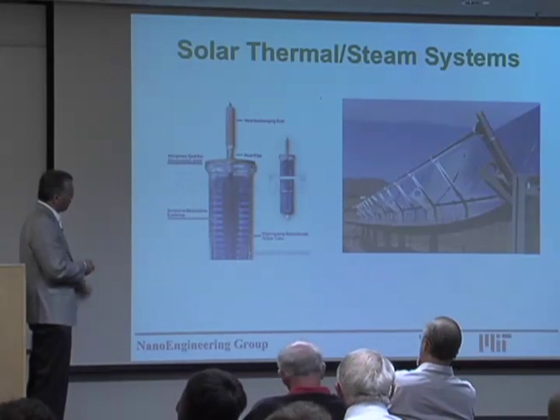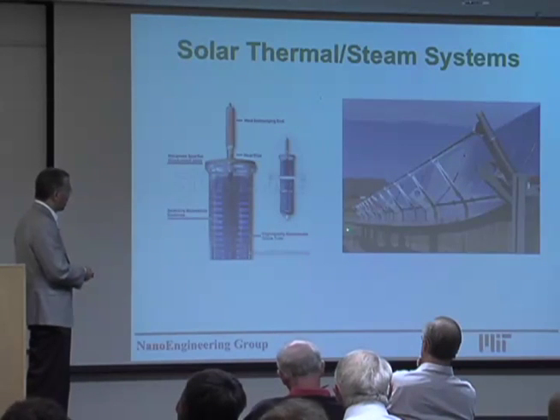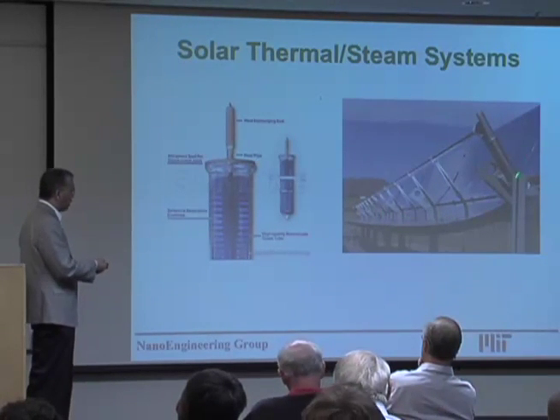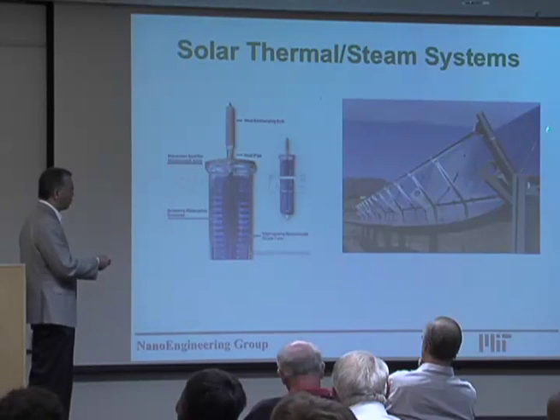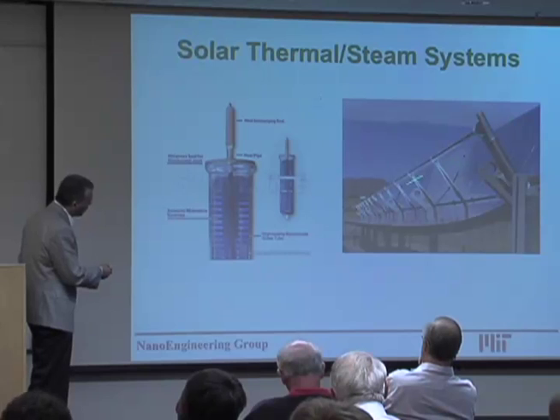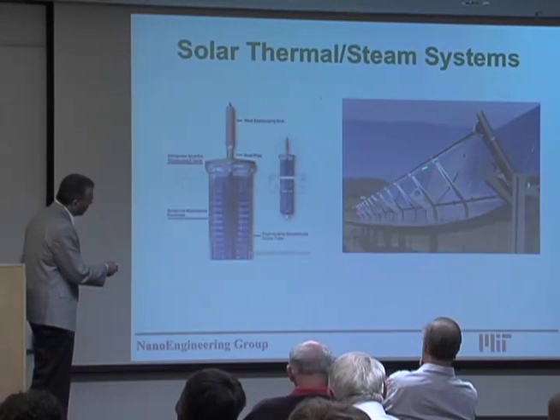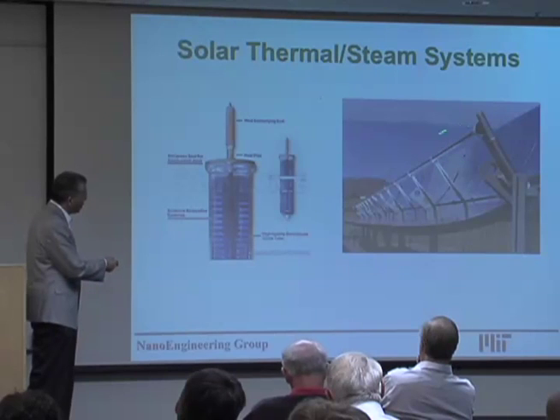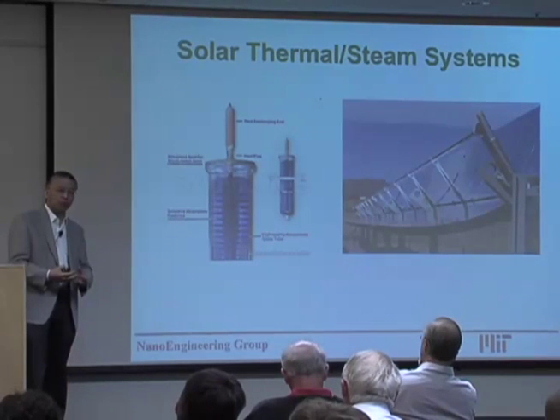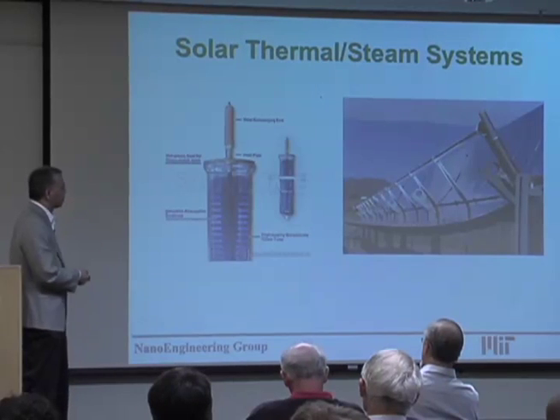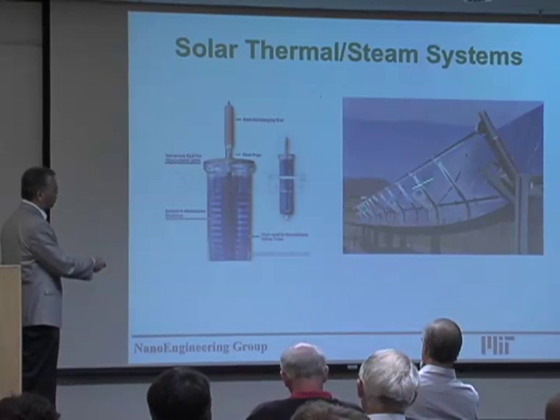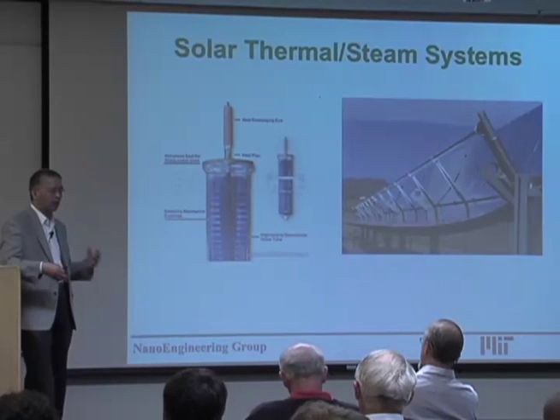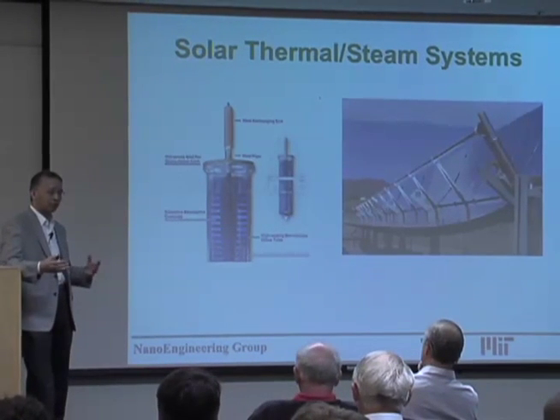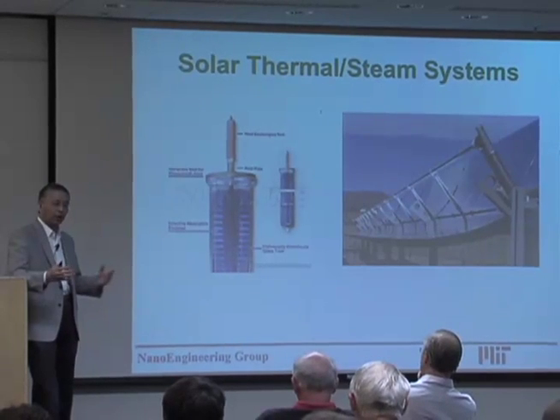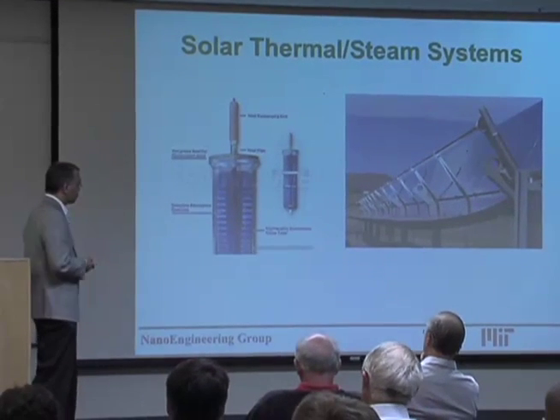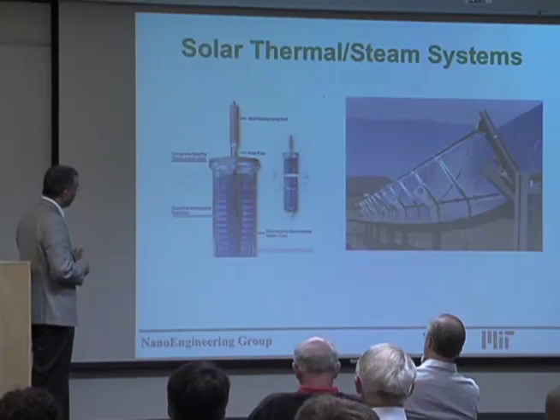And of course, to get to higher temperature, you need to concentrate. So here is a solar thermal power plant, parabolic trough. Again, it's a vacuum. Inside you can see it's black, outside is glass. It's an evacuated tube, and the solar radiation is focused into the center. The concentration is typically around 50 times, so 30 to 70 times in such a system. So that's the state of the art.